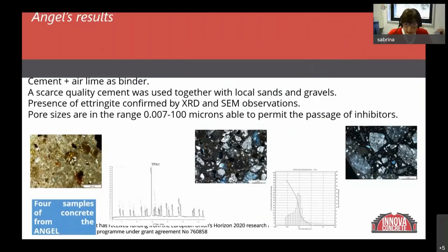Also for this monument, we report the results of the characterization analysis, and we noted a completely different type of binder that is composed of cement and air lime, but the aggregate is the same, and also the characteristic of the porosity.